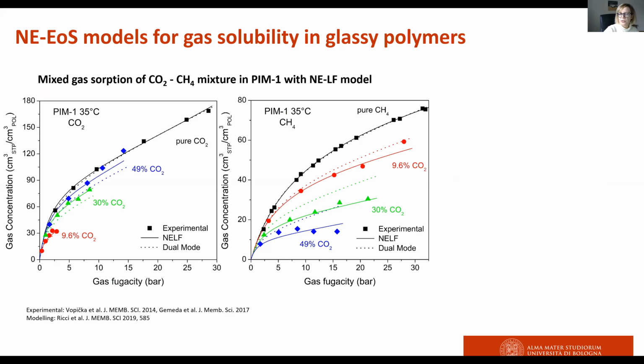Here, the solubility isotherms of CO2 and methane are calculated for different compositions of the gas mixture. The model allows us to represent the data very well at all gas mixture compositions, and in particular highlights the effect that methane solubility is very much reduced by the presence of CO2 in the gas mixtures, while the CO2 solubility is almost unaffected. This causes a reduction in the multi-component solubility selectivity with respect to the ideal case, the ideal value calculated based on pure component values.